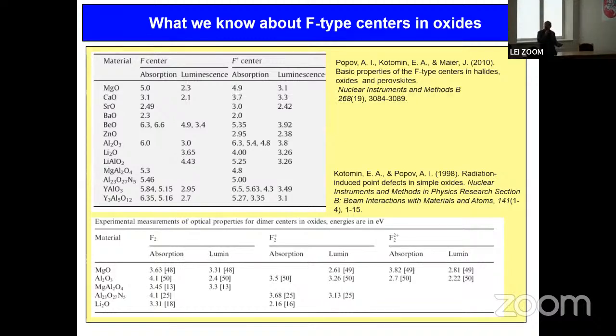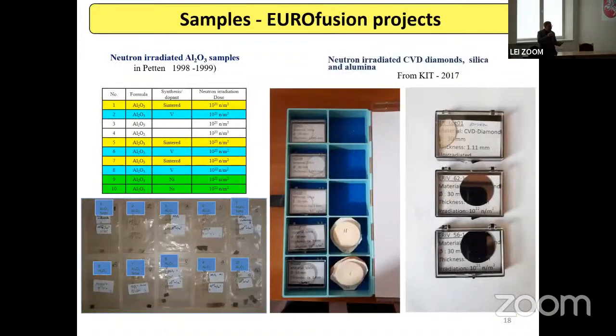For many years we were responsible for characterization of point defects in oxide materials. These are just two tables from our two review papers. What is important here is that for most of the oxide materials, simple F centers are quite well characterized and their properties are known. But if we are talking about more complex centers, so the F2 center is just two oxygen vacancies with two electrons. This is two oxygen vacancies with one electron. And let me show just some of our samples.